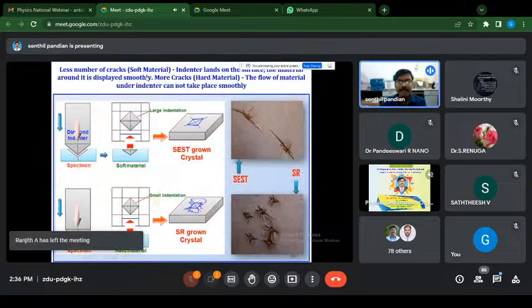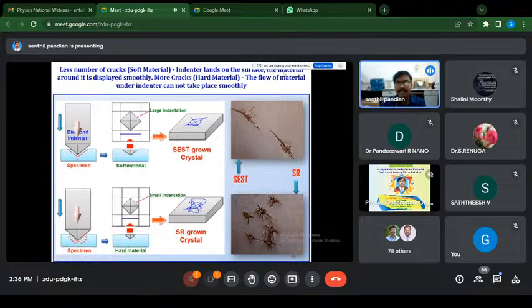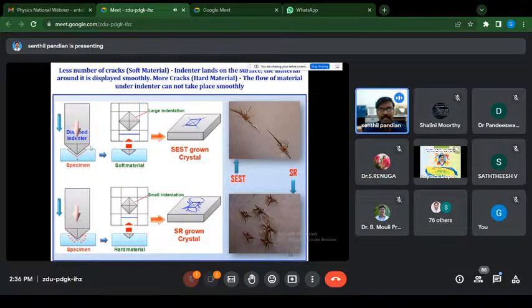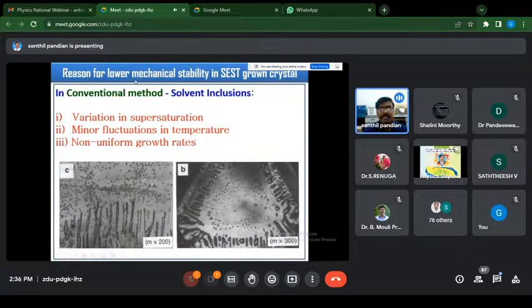The reason for the smaller number of cracks in the conventional method grown crystal is that when the indenter lands on the surface of the crystal, the material around it flows smoothly, so there are fewer microcracks. But the flow of material under the indenter cannot take place smoothly in a very hard material like the SR method grown crystal. So the reason for lower mechanical stability in the conventional method grown crystal is the solvent inclusion, and a variety of parameters such as variation in supersaturation, minor fluctuation in temperature, and non-uniform growth rates govern the solvent inclusion.